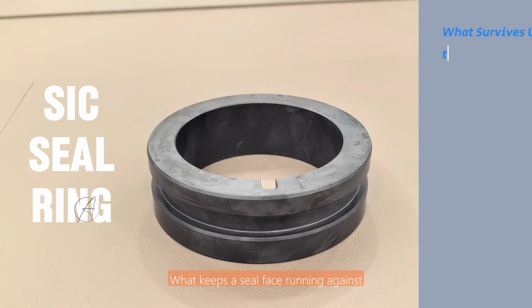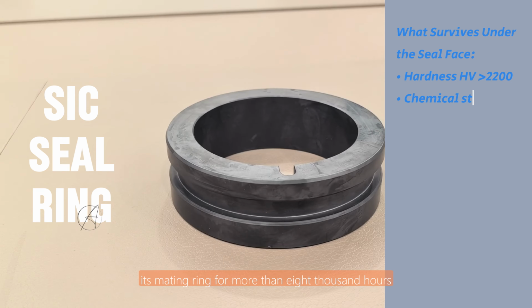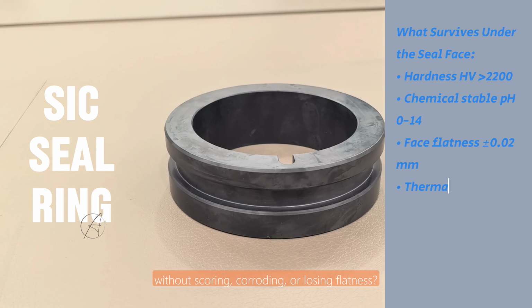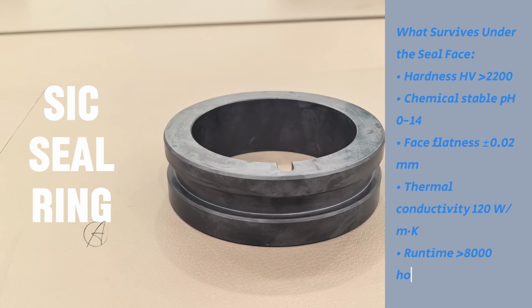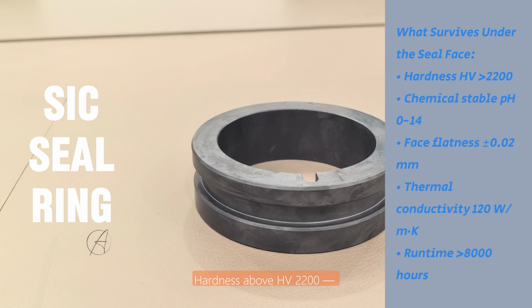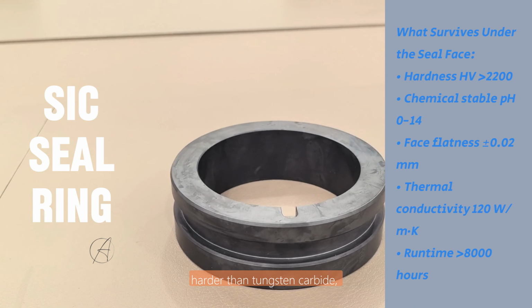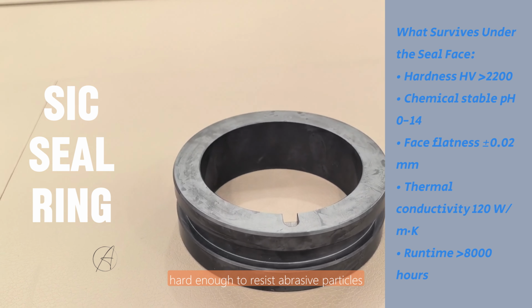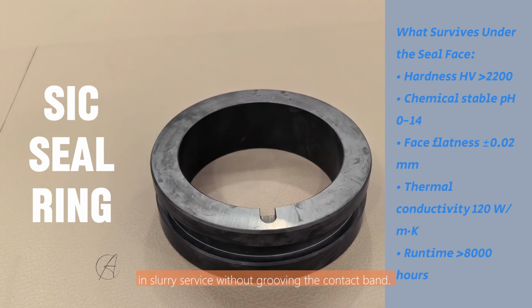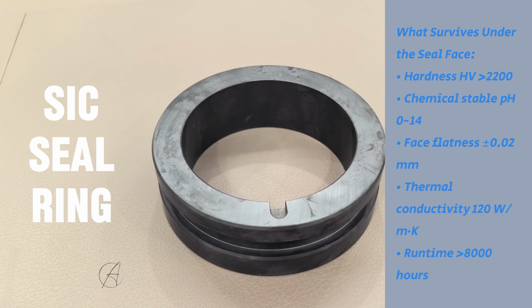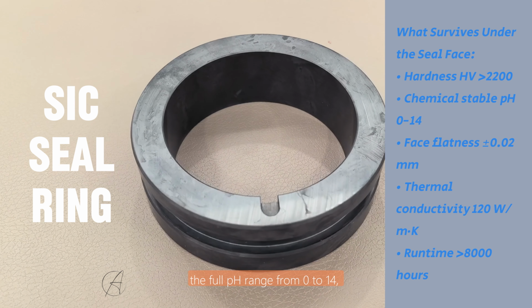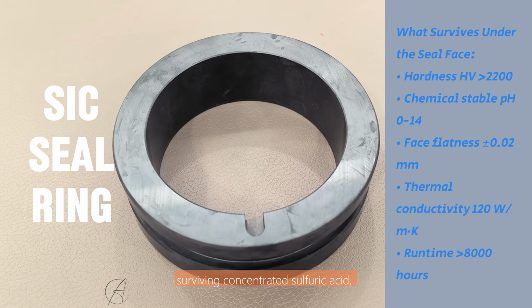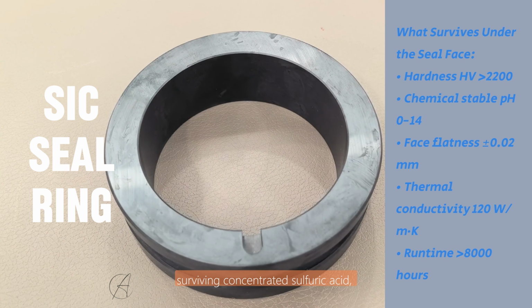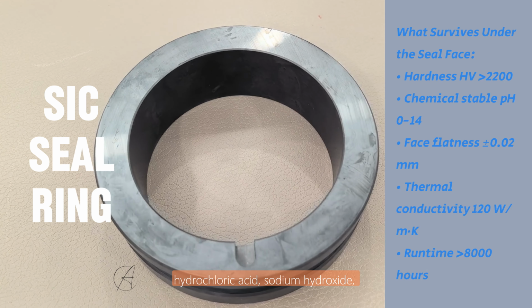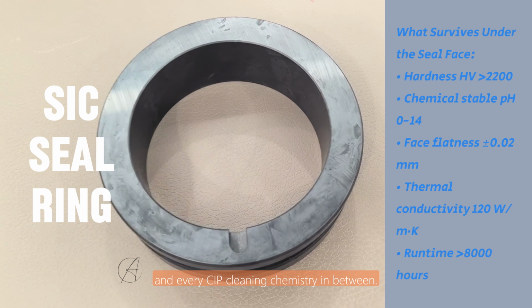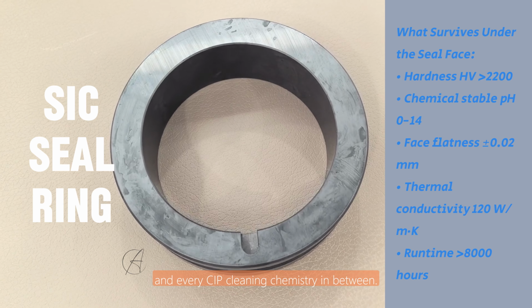What keeps a seal face running against its mating ring for more than 8,000 hours without scoring, corroding, or losing flatness? Hardness above HV 2200, harder than tungsten carbide, hard enough to resist abrasive particles in slurry service without grooving the contact band. Chemical stability across the full pH range from 0 to 14, surviving concentrated sulfuric acid, hydrochloric acid, sodium hydroxide, and every CIP cleaning chemistry in between.